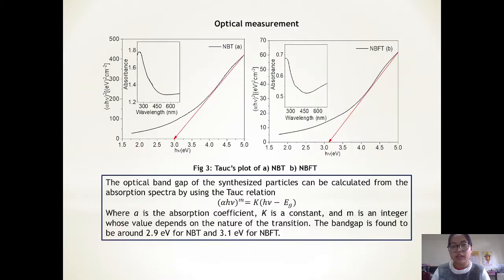Next, we have the optical measurement. The absorption spectrum of the samples was measured, and from the spectrum, the optical band gap of the synthesized particles was calculated by using the Tauc relation. The optical band gap of NBT was found to be around 2.9 electron volt, and for NBFT it was found to be around 3.1 electron volt.